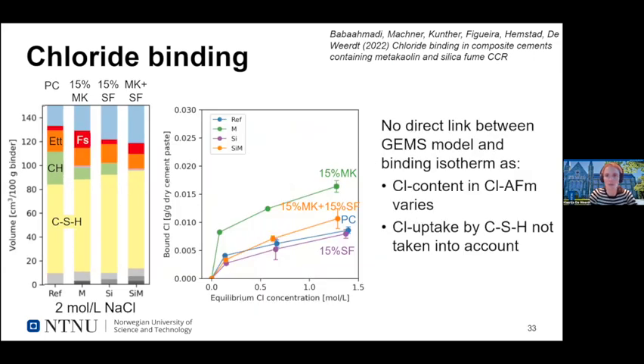So when Babaahmadi in her study wanted to link these phase assemblages to the binding isotherms, where she actually measures the amount of chloride bound per gram dry cement when varying the chloride concentration, she couldn't match these binding levels with the phase assemblages predicted by GEMS. And the reason why there is no direct link between the GEMS model and the binding isotherms is that we observed that the chloride content in the AFM actually varies, and it's not necessarily the value you get from GEMS. And you're not accounting for the role of CSH in the physically adsorbed chlorides. So here you can see that we need some more research on some of the thermodynamic data to actually be able to do this.